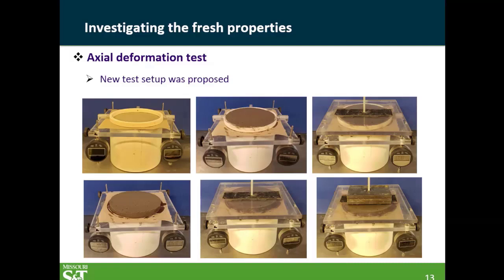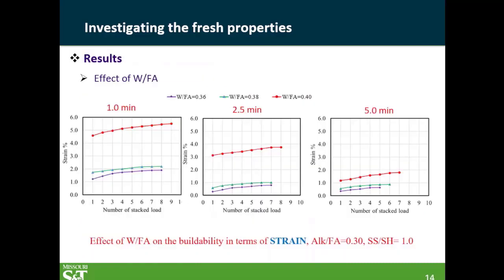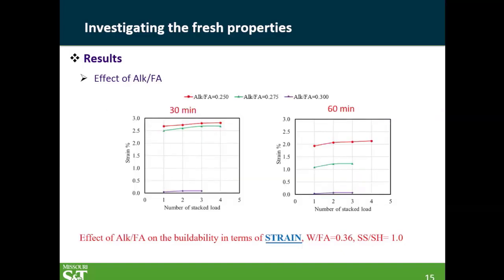this layer of printed concrete. And then based on what is the tolerance for deformation, you can pick how many layers you can add, and then you can link this back to your cycle time. Here are some results for different cycle times: 1 minute, 2.5, and 5 minutes. As you would expect, with increasing the number of stacked loads, you get more strain. And again, you would see much lower strain here, for example, with a cycle time of 5 minutes, and very high strain here for a very short cycle time.